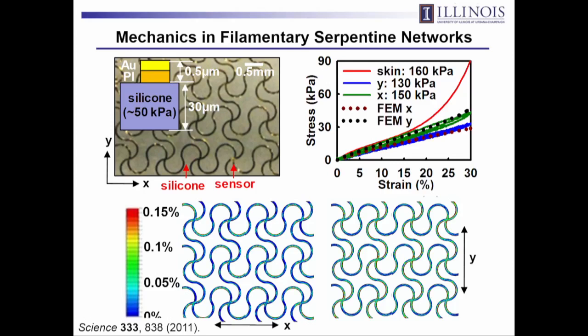So here's a stress-strain curve for skin. It starts to go sort of nonlinear. It starts to rip and rupture, as I mentioned before, at about 30% strain. But it's linear elastic up to about 15% strain. If you look at this composite structure, you measure it experimentally, you see an effective modulus, a slope here, of about 130 kilopascals, in spite of the fact that you've embedded very hard materials into that platform. Again, 150 gigapascals for silicon. You have an effectively soft material, quantitatively matching up with the finite element modeling results.